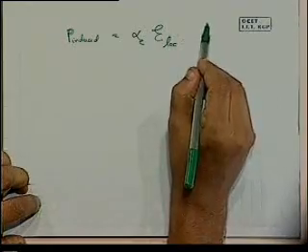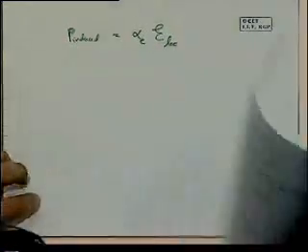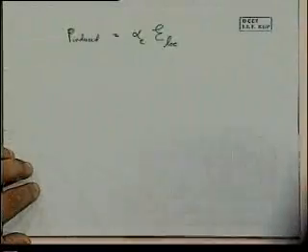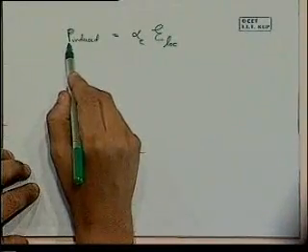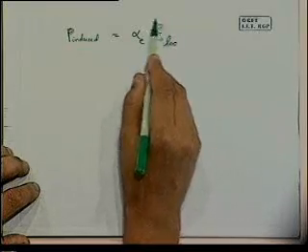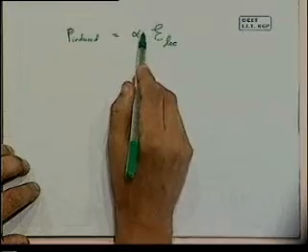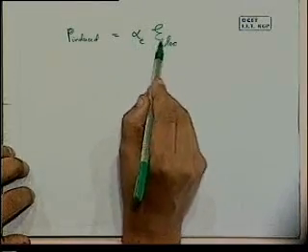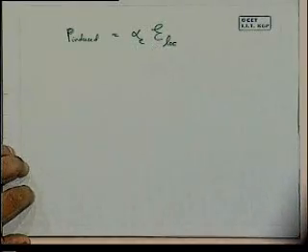Previously we assumed that for any individual dipole, the dipole moment was given by alpha E times the field, from the previous lecture. Now last time, to arrive at this particular expression, we did a number of steps, but it involved the idea that the induced dipole moment, small p, is equal to alpha E times the applied field. What we are doing is making a correction here for the applied field and actually using the real field that that particular dipole will experience, namely the local field, which we just expressed in terms of the applied field and the polarization.